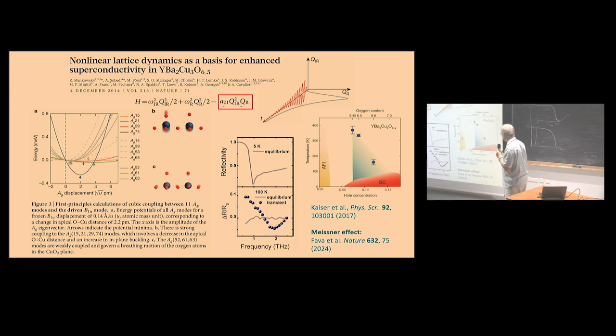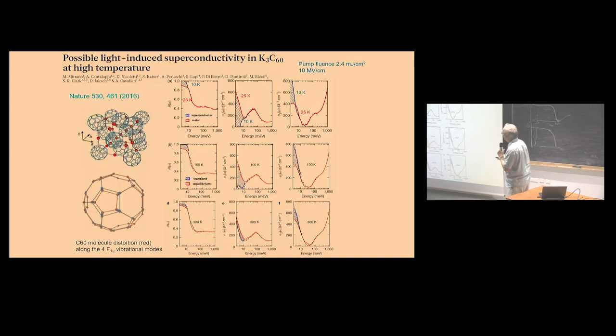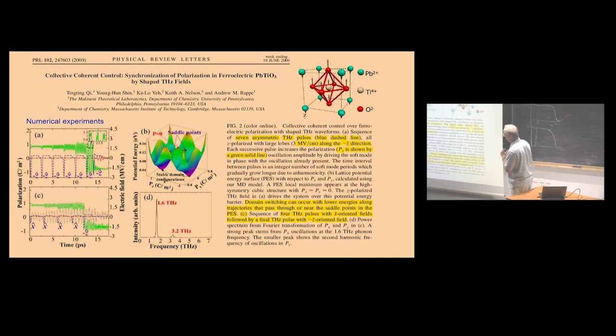And it was published last year, again by the group of Cavalieri, that they were able to see the Meissner effect in such terahertz pumped superconductors. It was observed in more superconductors like this fulleride system. Again, you have a decrease of conductivity and enhancement of reflectivity. I will not speak about it too much, but let's go to ferroelectrics, because many people here are from the ferroelectric community.